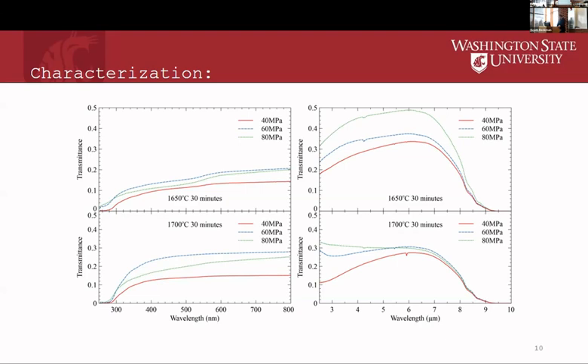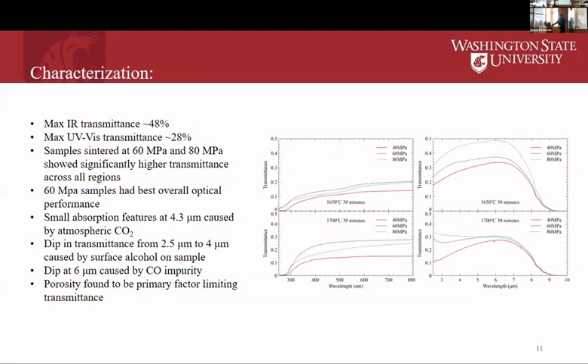You can see some peak assignments here. At the 4.3 micron region, we have a little dip in a few of our samples, simply due to atmospheric CO2 in the chamber we were measuring our samples in. We also have a dip at 6 microns in one of our samples, which is due to carbon monoxide. And we have a broad stretch between 2.5 and 4 microns that's due to an OH impurity, from alcohol.